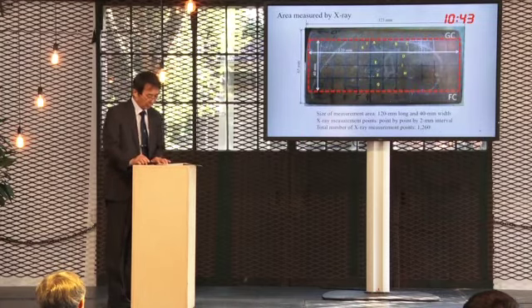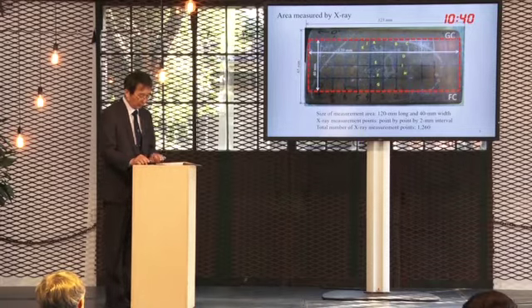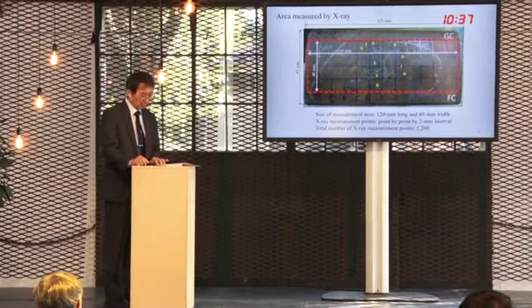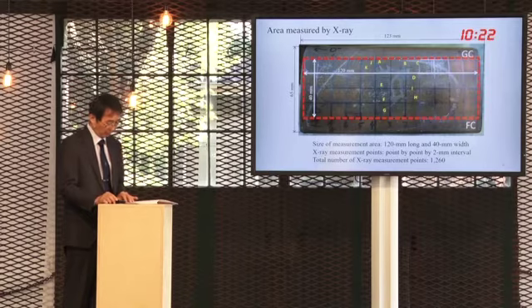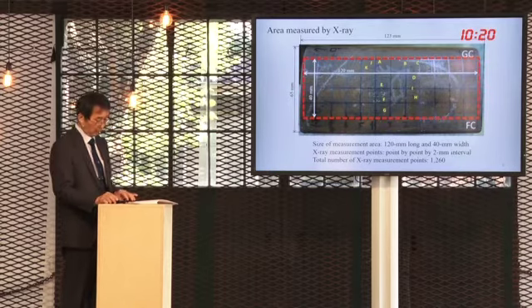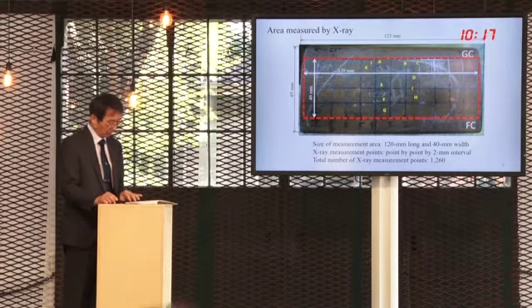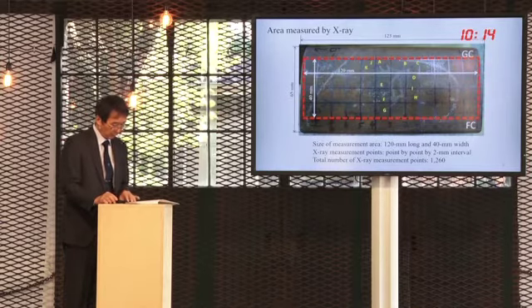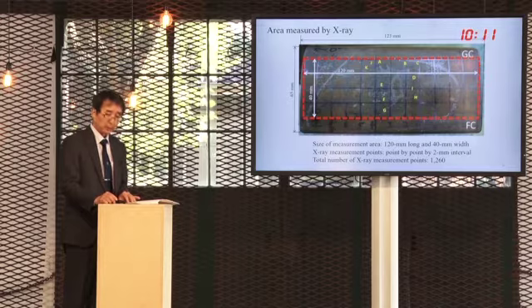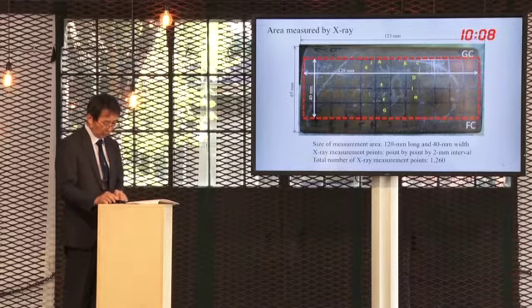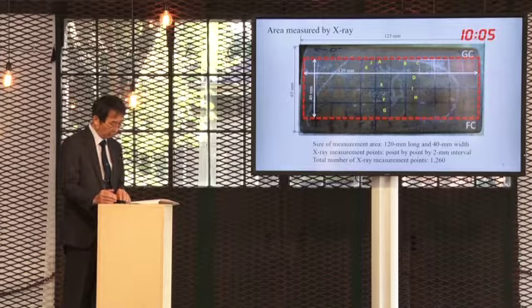This picture shows the sample surface of the rail head. The X-ray measurement was carried out on the rectangular area shown by the dotted red line in the picture. The length of the area in the longitudinal direction was 120 millimeter, and the transverse length was 40 millimeter. The X-ray measurement was conducted in this area with 2 millimeter interval. The total number of X-ray measurement points was 1,260.